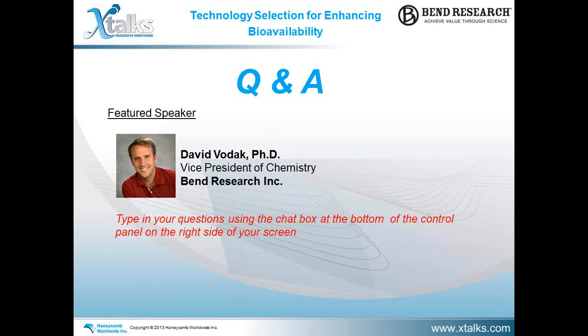Okay, thank you. Our next question here: what determines selection of loading in spray-dried dispersions? Well, as I tried to cover with the spray-dried dispersion map, the two things that determine the selection of the loading in an SDD are the melting point to glass transition temperature ratio and the LogP. So things that have a high Tm over Tg ratio are typically much harder to stabilize in the amorphous state, and therefore you have to dilute it out with more of the high Tg polymer. And on the other side, things that are very greasy and lipophilic can have dissolution rate issues, so you have to limit your loading of that greasy compound in order to have something that continues to dissolve, as was exemplified in the Kaletra SDD case, where we knew right away that it was going to be hard to have much higher than a 10% active loaded system.